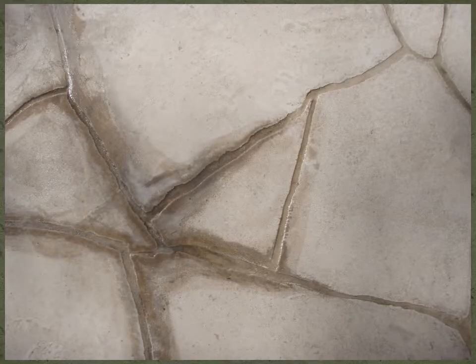This is extreme mineral staining on a limestone floor where there was a puddle, a low spot in the intersection of these grout joints. And the floor is actually in the middle of a cleaning process where I'm applying extra chemical here to try to melt this silica buildup with ammonium bifluoride cleaner. But this is just typical of how it gathers along the edges and fills up the grout joints.